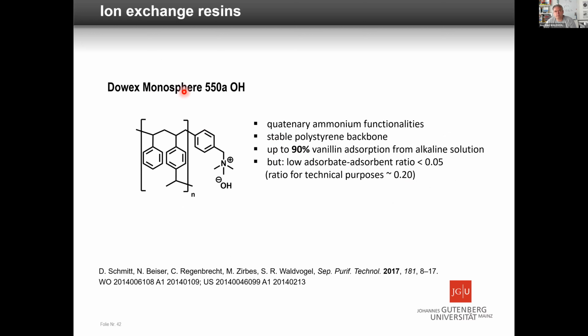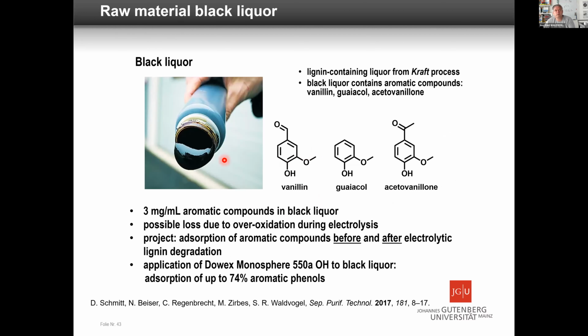We can use the simplest one out of there. This is the one which comes in with water filters, and it's the simplest one which is available, and you easily get 90% of the vanillin out of the alkaline solution by simply rinsing it over the system. You can even use black liquor, and you get it directly from the black liquor. It's not much in there, but you can get all of these guys out of it. And by simply pumping the diluted version over it, you get 74% of the aromatic phenols out of it.